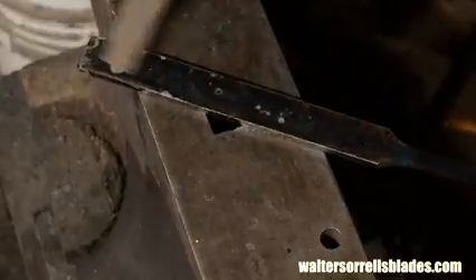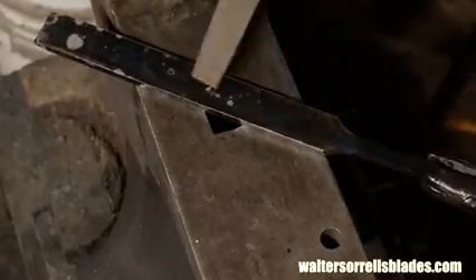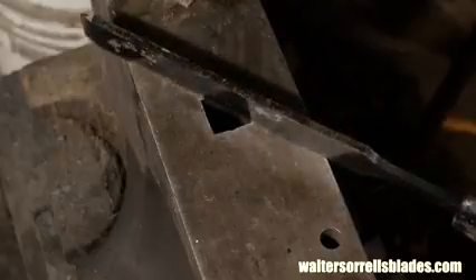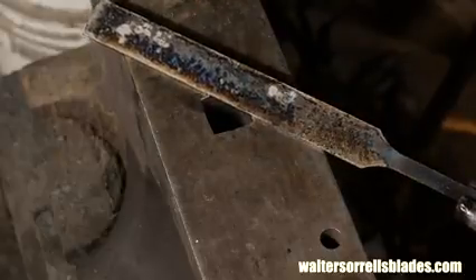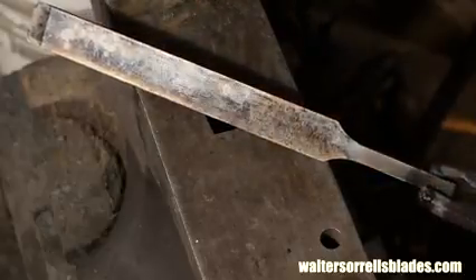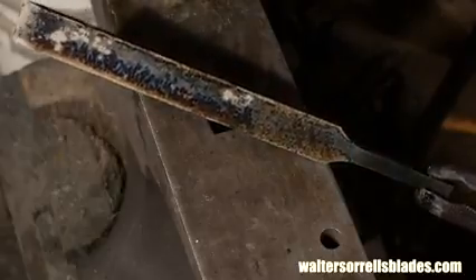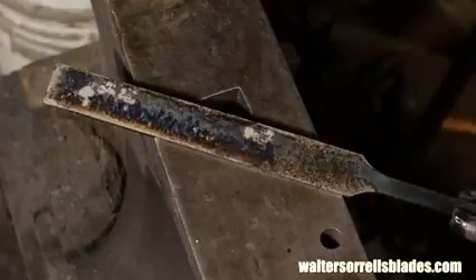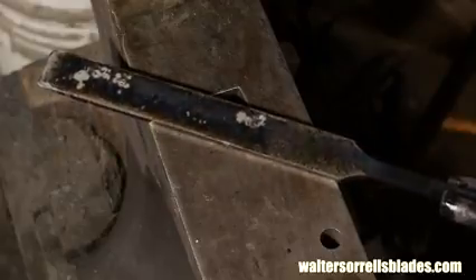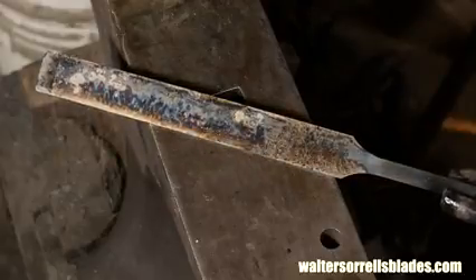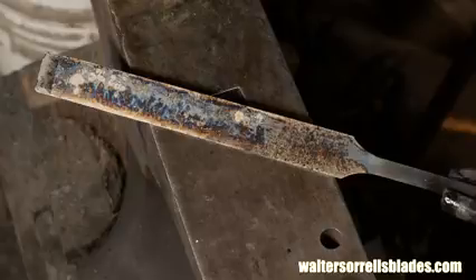I'm going to test that the hardening process actually worked by gently rubbing the corner of a file on the steel. If it sort of skates over the steel, I know that the steel has hardened properly. But if that corner kind of bites into the steel, you screwed up and you need to try again. But that's not a problem. You can repeat the hardening process several times without damaging the steel. But this looks fine.